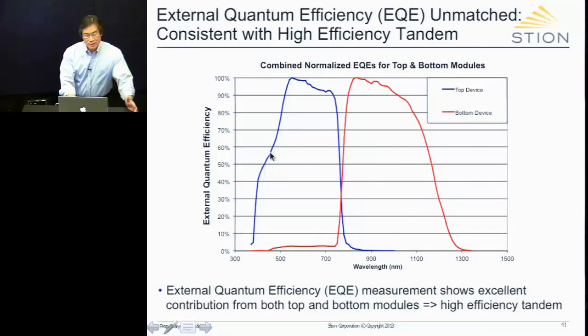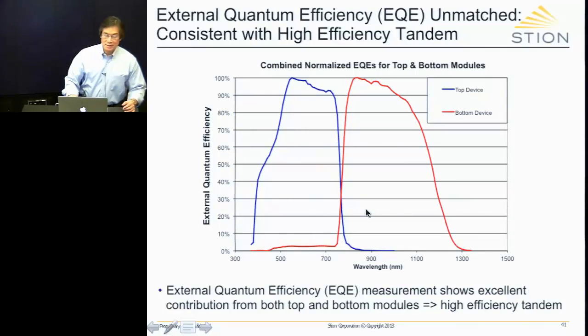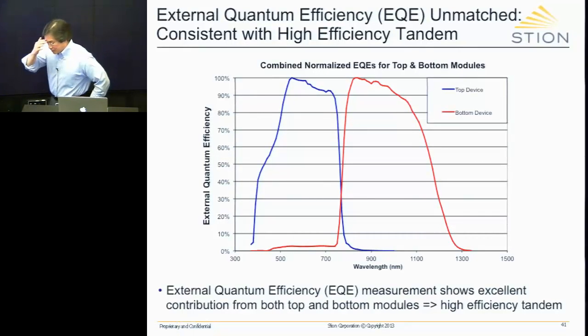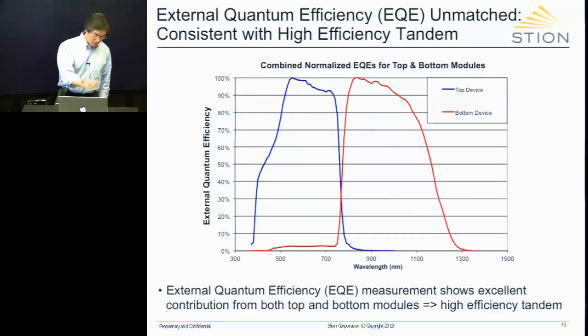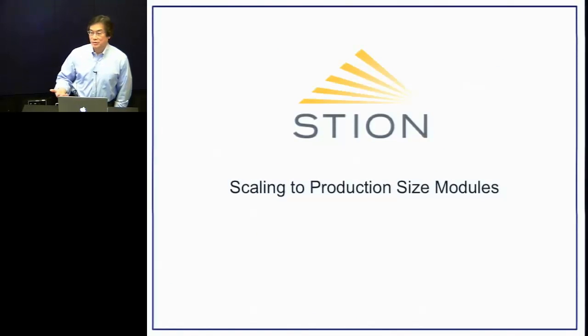This drop-off here is because at the time we were using cadmium sulfide as the emitter for the top device. And so the band gap is a little bit low, so you see a chunk being taken out of that. But the first thing to notice is that the contribution from the top and the bottom device is quite good. Another thing to notice is that the onset at low energies is very sharp, particularly for the top device. And that's important because it tells you that we're extracting as many of the carriers from the back of the device as possible.